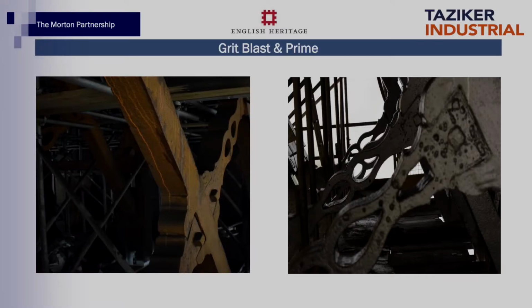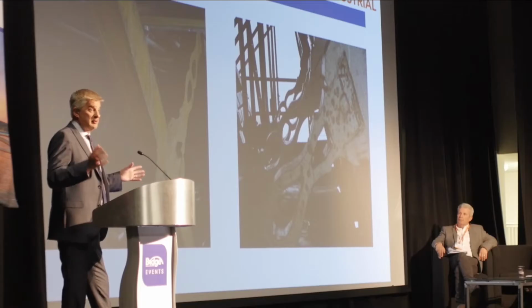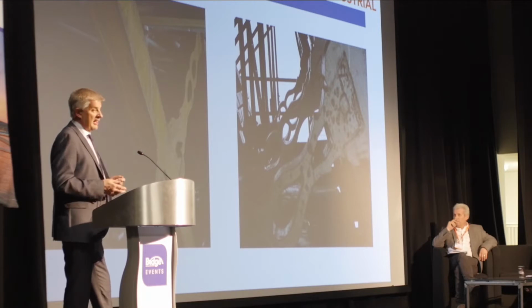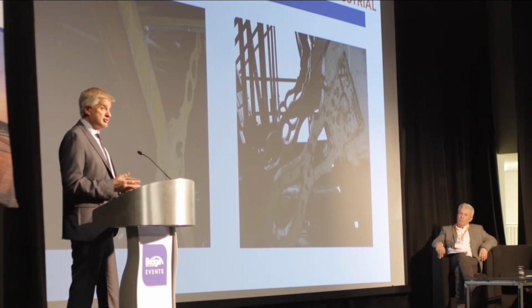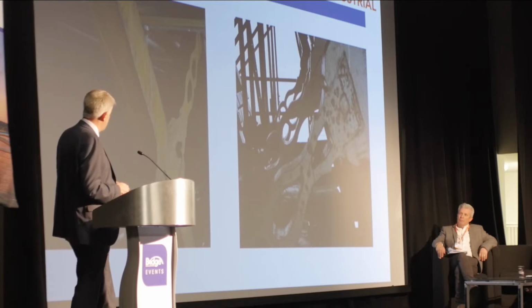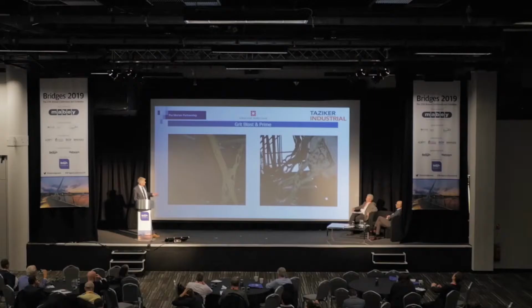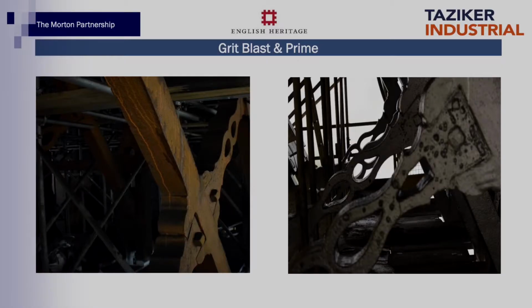As part of the initial concept behind the tendered works was to spot blast the structure, so that was purely to remove corrosion in the worst case scenarios. However, we found as we started to do that work that there was going to be quite a lot of problematic areas with the interfaces where we were leaving existing coating. So we managed to value engineer the project by negating some of the areas that were down for blasting, like the road deck, which we were going to be covering with a waterproofing membrane, and actually went with a full SA 2.5 grit blast to remove as much of the existing coating as possible. So there you will see on the left, obviously when it was first flash blasted before we went back over it, and obviously one of the radials over on the right.